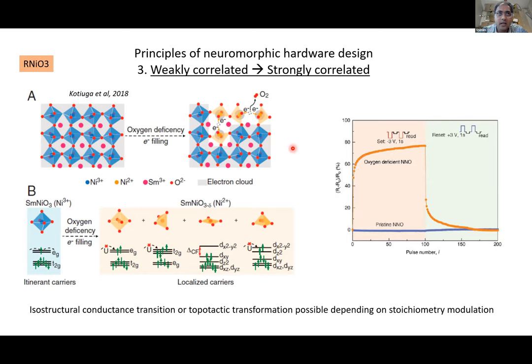The second is the structure is related to the valence stability. So if you can stabilize the valence, regardless of the epitaxial stabilization of the structure, then the epitaxy simply does not matter, because you're electronically modifying the orbital occupancy. That is really the central mechanism for resistance modulation. So if you can accomplish that without relying on a substrate, then you can do this. This is where the high pressure, low pressure, et cetera, come in. Thermodynamically, you can alter the oxygen potential to create the right phase.